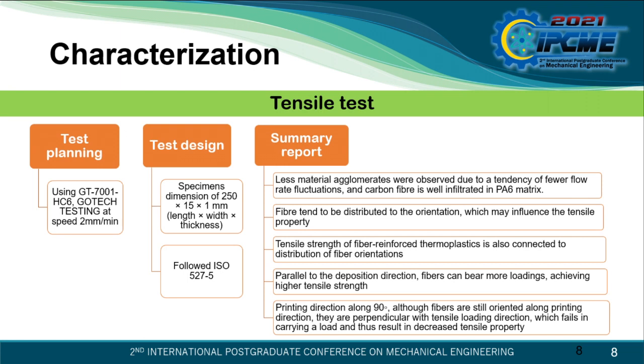Second, fibers tend to distribute in orientations which may influence the tensile properties. The tensile strength of fiber reinforced thermoplastic is also connected to the distribution of fiber orientation. We can see the distribution of fiber orientation in the previous slide. Parallel to the deposition direction, fibers can bear more loading, achieving higher tensile strength. The parallel to the deposition direction we can see in the 0 degree angle. Lastly, printing direction along 90 degree: although fibers are oriented along the printed direction, they are perpendicular to the tensile loading direction and fail to carry the load, thus resulting in decreased tensile property.